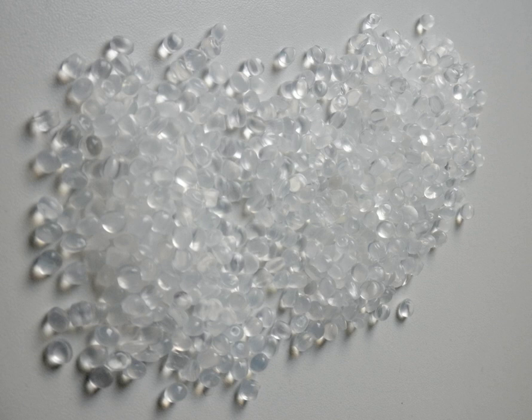In 1953, the German chemist Karl Ziegler developed a catalytic system based on titanium halides and organoaluminium compounds that worked at even milder conditions than the Phillips catalyst. The Phillips catalyst is less expensive and easier to work with, however, and both methods are heavily used industrially. By the end of the 1950s, both the Phillips and Ziegler type catalysts were being used for HDPE production. In the 1970s, the Ziegler system was improved by the incorporation of magnesium chloride.